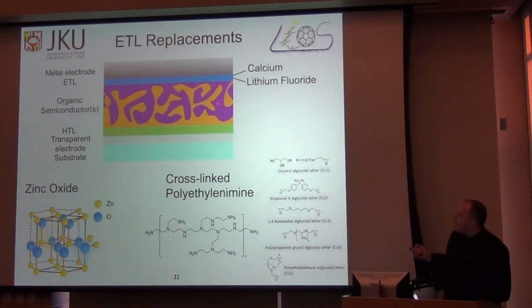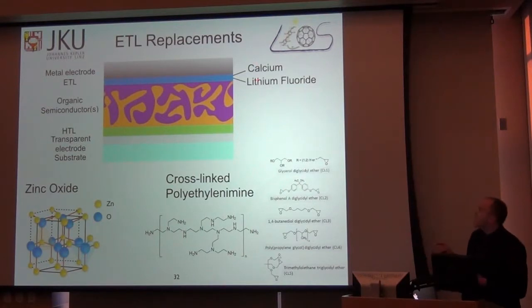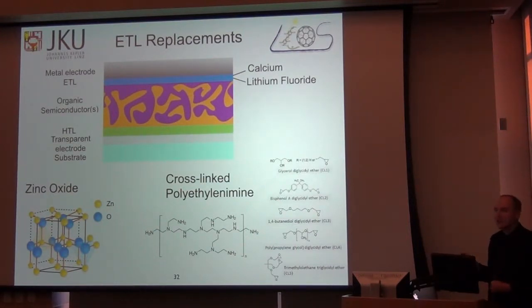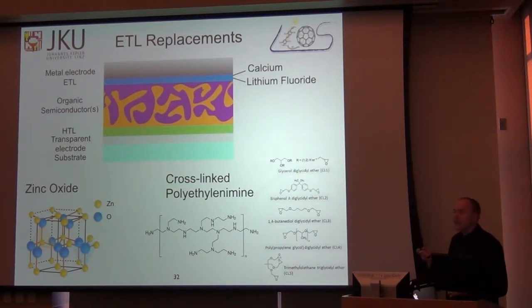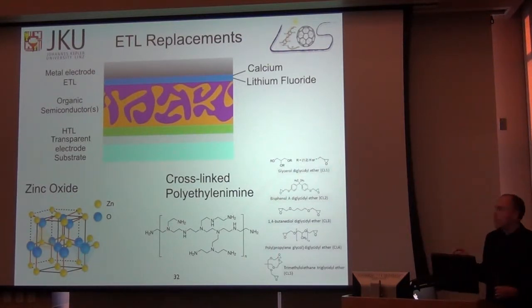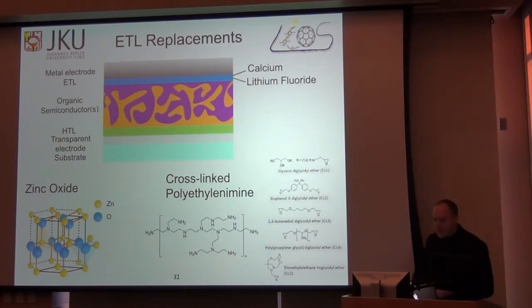And if you look at the conventional device architecture, at the time, calcium and lithium fluoride and aluminum as the metal back electrode were the most common materials used. And these aluminum, and especially calcium and lithium fluoride, are extremely air sensitive. So these are the materials that would react within minutes. And so what we did at first was we wanted to replace this with something significantly more stable. And I'll present some results here that show that we've used zinc oxide, more recently this cross-linked polyethylenimine, with some reasonable success.